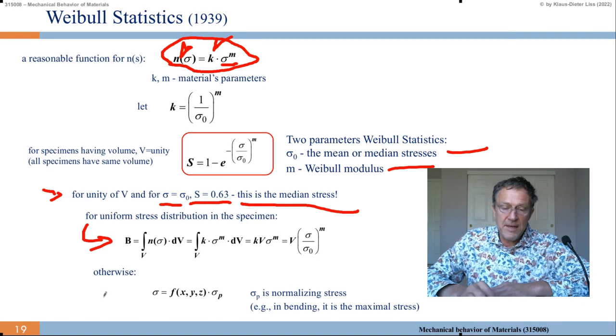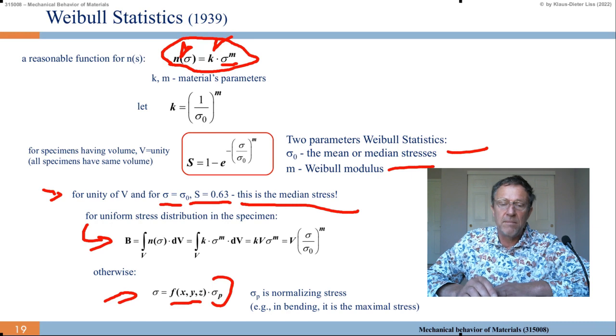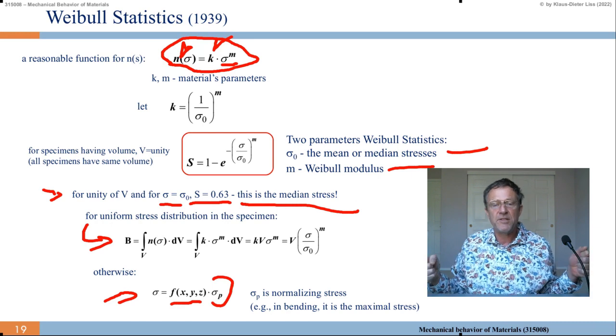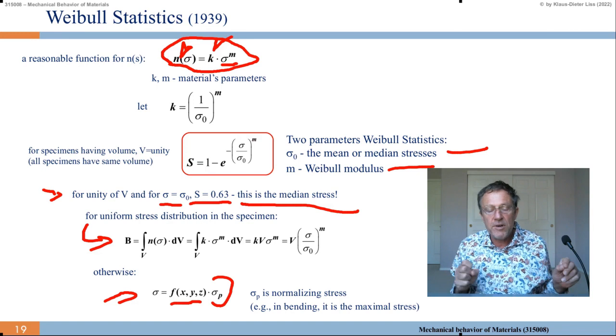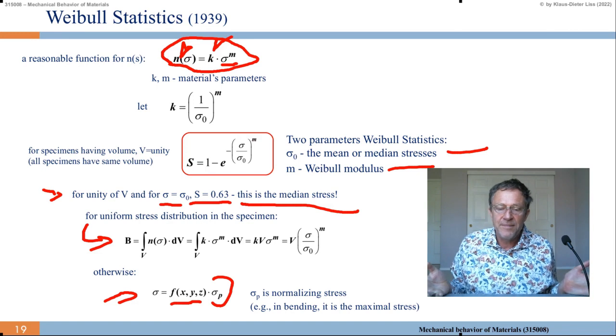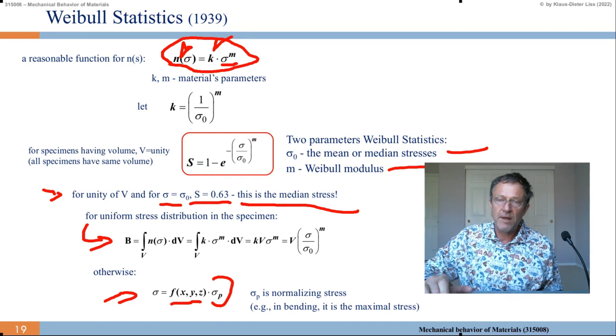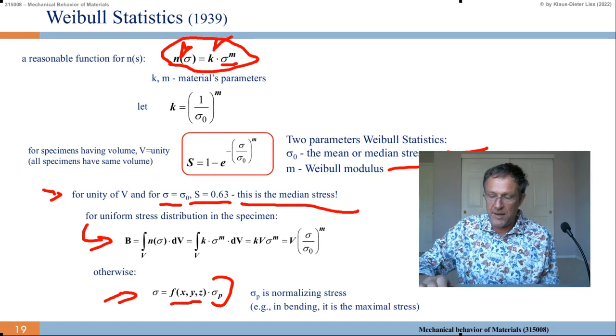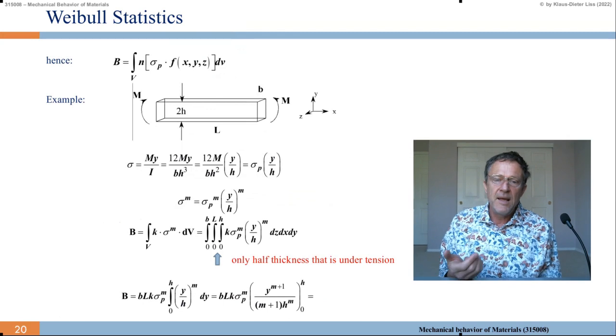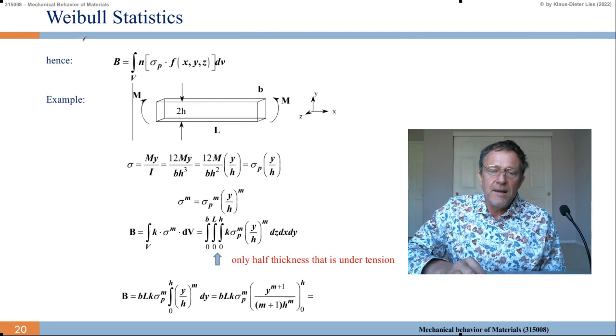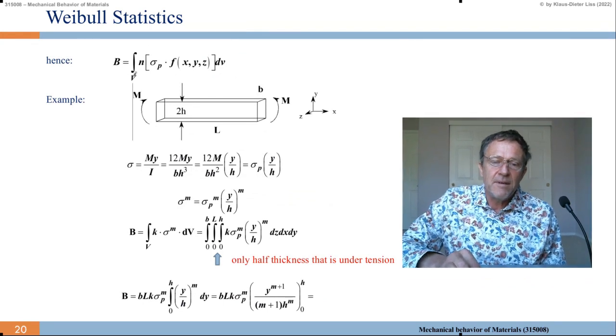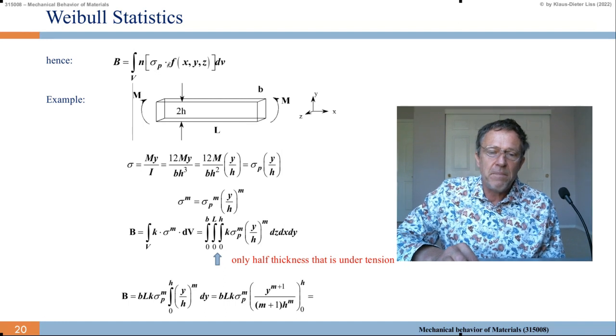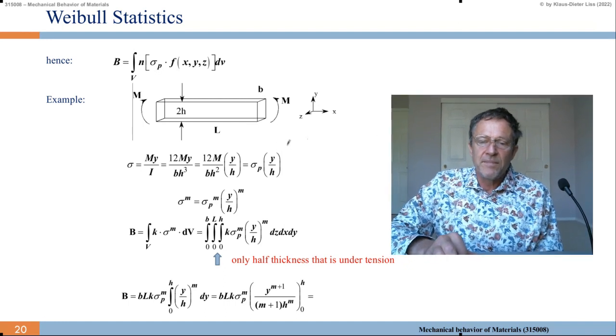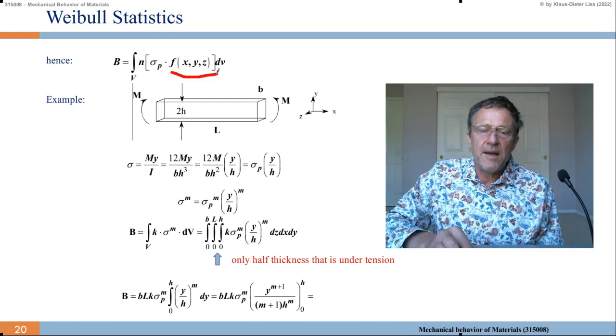On the other hand, sigma is a function of xyz times some normalizing stress, sigma p. Let's say sigma p can be the maximal applied stress in your experiment. And then the sigma in the whole sample is a function times that stress. Stress can be higher, stress concentration, can be lower in other regions of the material. So hence, the B becomes this integral now over sigma p times this function dV, and this function we can calculate already.